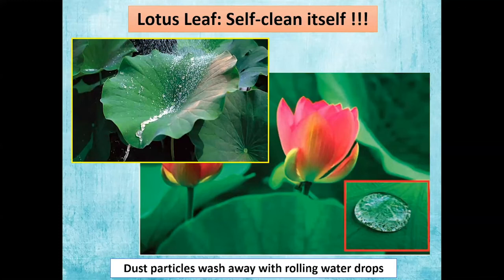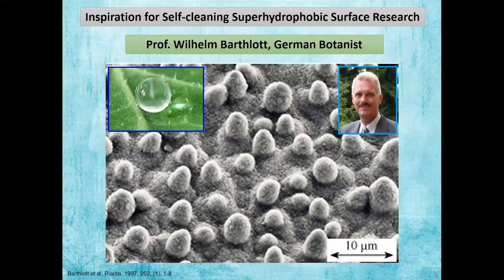The superhydrophobic surface is inspired from the lotus leaf, and you might have observed that the lotus leaf is always clean and always green. That is because even if some dust particles accumulate on the lotus leaf, during the rainy season the falling water drops can take away all the dust particles while rolling. When a water drop sits on the lotus leaf, the contact angle is more than 150 degrees, so we can say it is superhydrophobic. And if you tilt it less than 10 degrees, the water rolls off the surface. So it has a very low sliding angle. We know why this lotus leaf is highly water repellent.